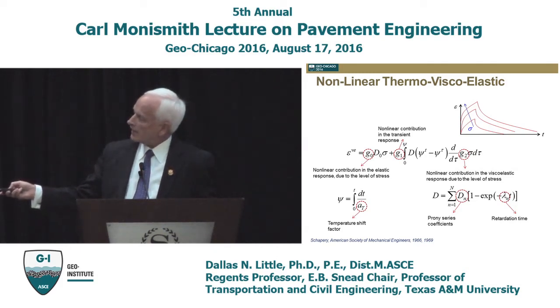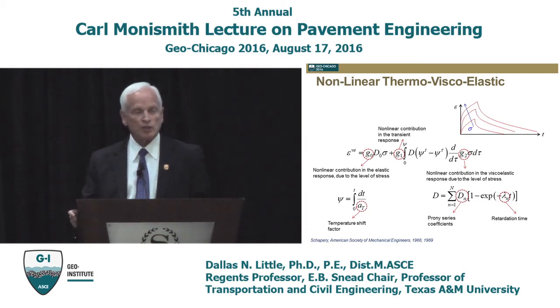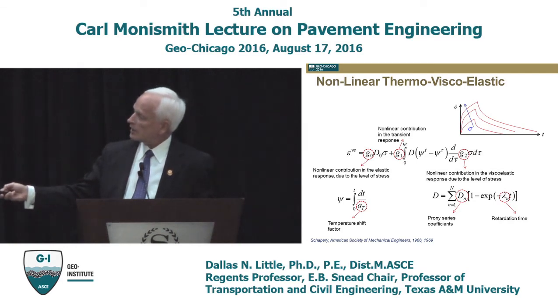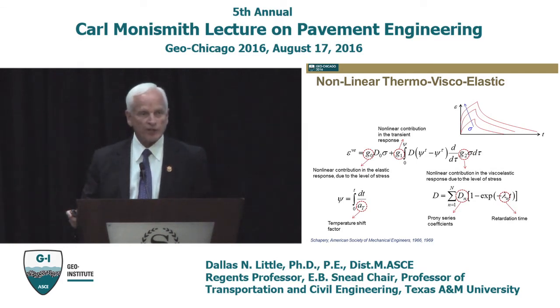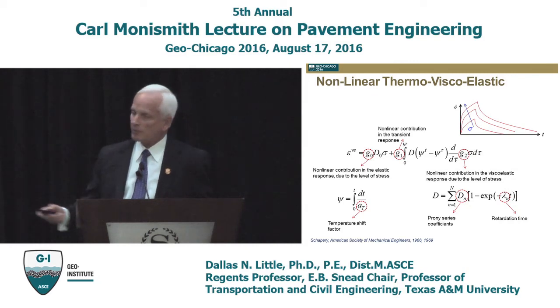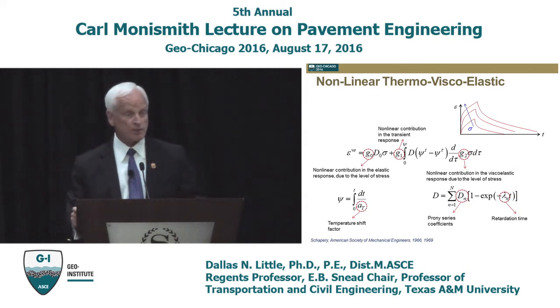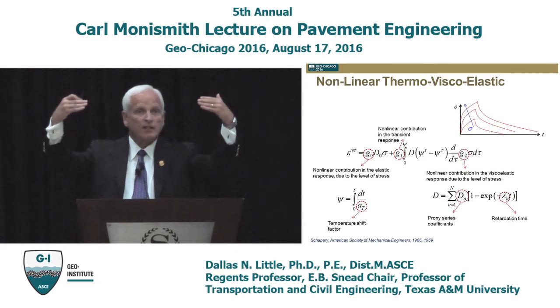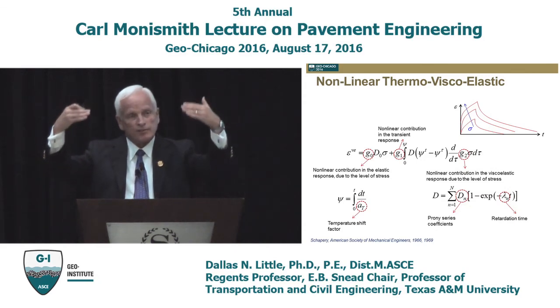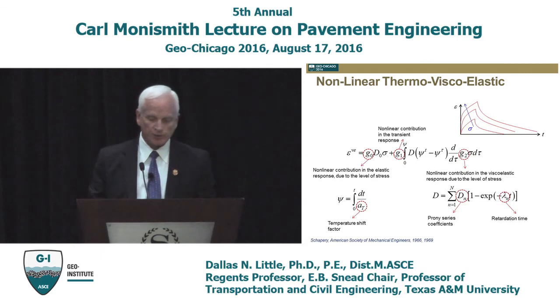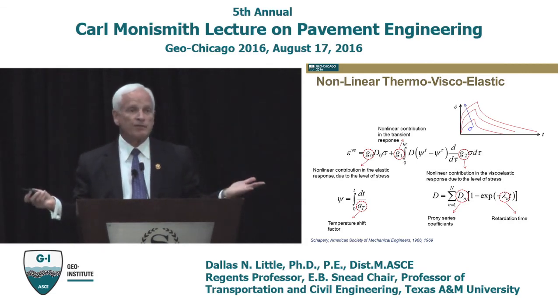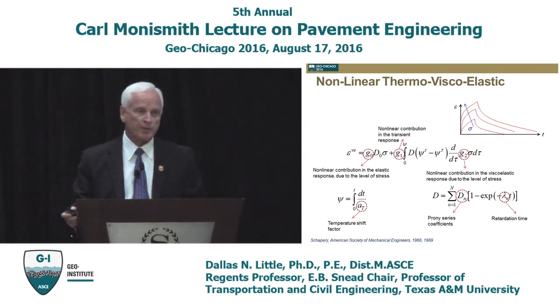And we find it more convenient to model the transient compliance using a Prony series, where d sub n represents the coefficient and the lambda sub n represents the relaxation times in the Prony series that define the viscoelastic response, defined by a series of Kelvin systems in the model. So we accommodate viscoelasticity, to make a long story short, and we accommodate nonlinear viscoelasticity.